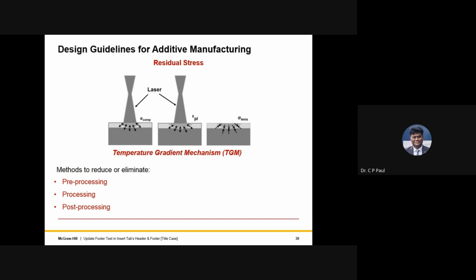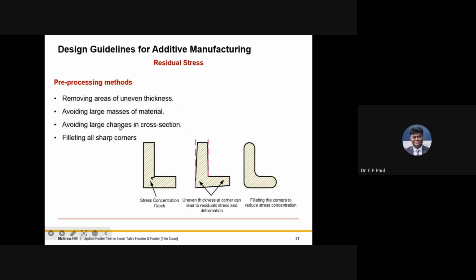There was a discussion on the residual stress during additive manufacturing. So we have to focus on the temperature gradient mechanism. For example, I always tell the students that if you put a whole plate into a furnace, the whole component is heated, and when it is cooled, the whole component is cooled. But this is not happening with lasers. When you put the laser on a substrate, the substrate expands locally because of the temperature, and you have stress coming from that.